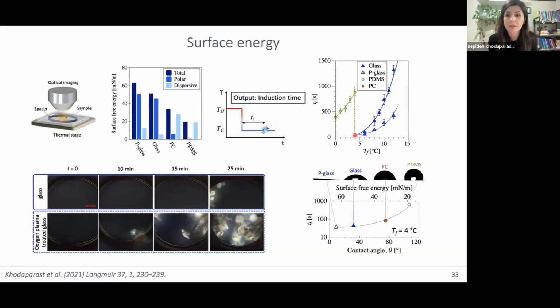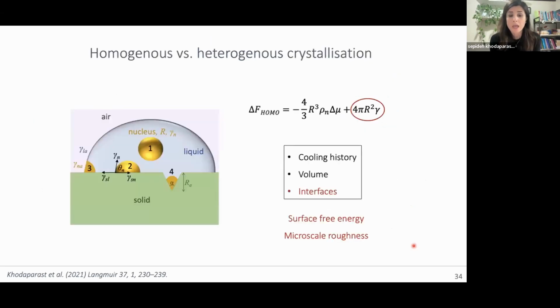But what you can see here is, again, the induction time, the time to the observation of the first crystals. You see that it's much longer for surfaces that have lower energy, so less wetting surfaces, compared to surfaces that are far more wetting, such as plasma-treated glass. And if I plot the water contact angle on the x-axis, you see that the induction time for crystallization to occur just increases monotonically with the wetting of the substrate. So that was just with the surface energy.